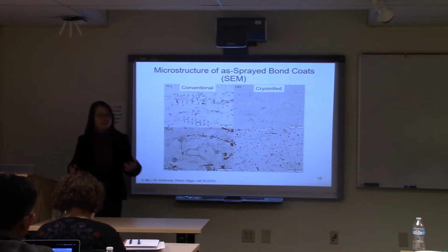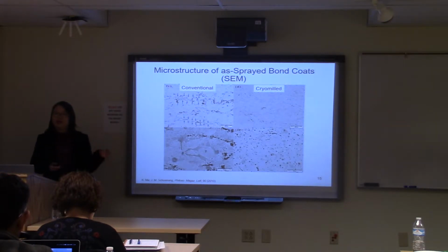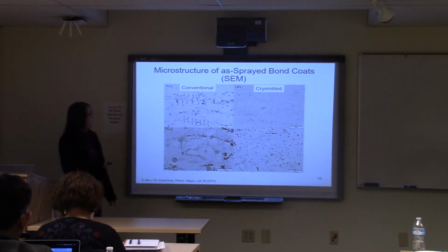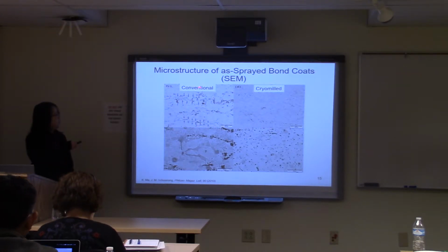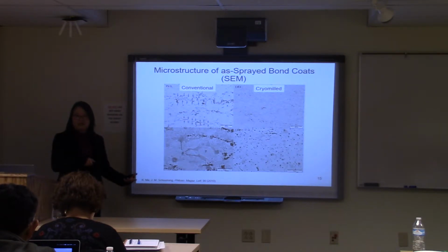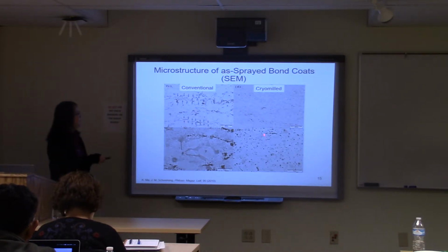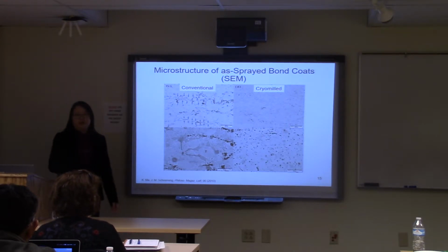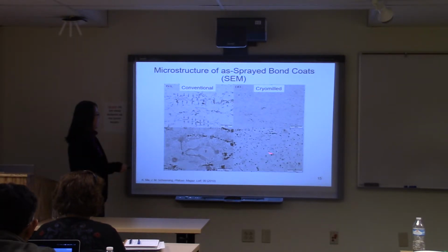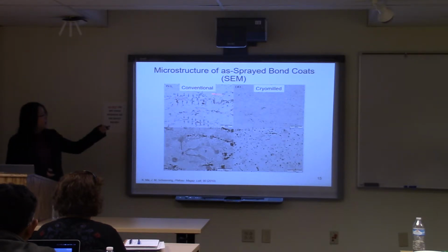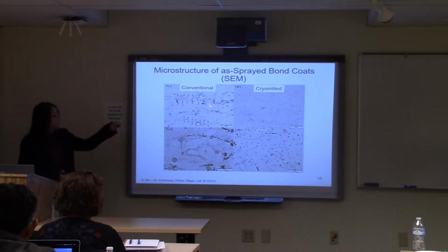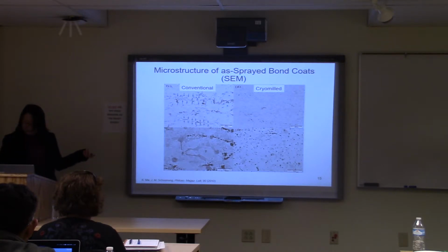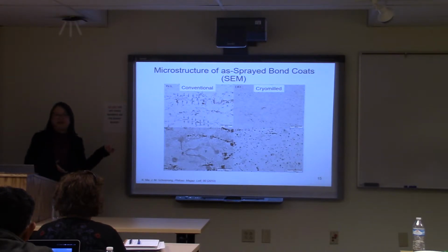So we're using this nanostructured powder. Now we want to see what the microstructure looks like when we spray it and make the bond coat. On the left, you are looking at what I call conventional, made from the gas atomized powder, so it has a coarser grain size, like 2 microns or above. On the right, the cryomilled one, we're using the nanostructured powder as the feedstock. You already notice the distinction. You get continuous interpass oxidation in between the high velocity oxyfuel spraying passes, and that's a very well established phenomenon people have reported.